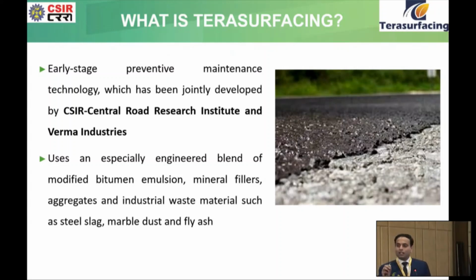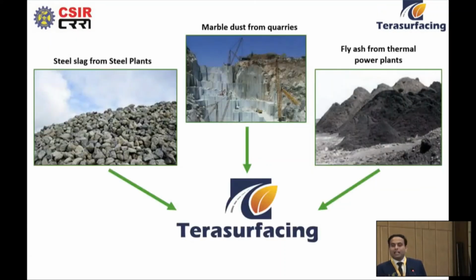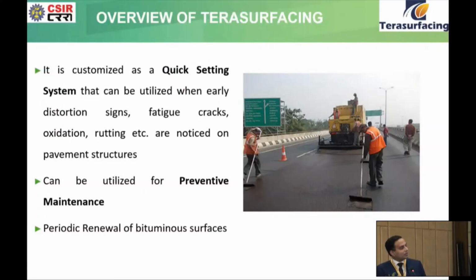It is completely an ambient atmospheric temperature based technology which does not involve any heating of bitumen and aggregate. All of you might have heard about the micro surfacing technique, where an 8 to 10 mm thick layer can be laid on the road surface as a periodic renewal or for preventive maintenance. In place of that, Terra surfacing is specifically based on industrial waste steel slag. With the help of it, you can lay this special treatment with a micro surfacing machine on distressed bituminous road, and we can prolong the service life of the existing bituminous surface. We carried out successful implementation of this technology in 4 locations in India.